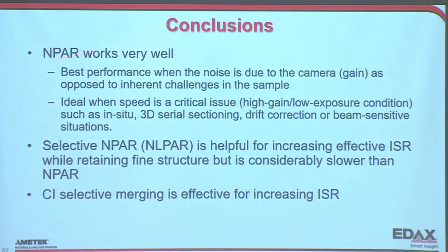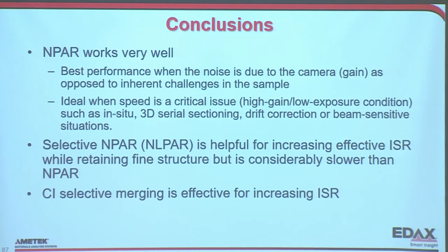So what are my conclusions? NPAR is great. It works well. But it works best if there's speed or noise from the camera as opposed to real challenges in the sample. And what that tells me is you can't use NPAR as an excuse for not polishing your samples. You still have to polish them and do the best job you can.